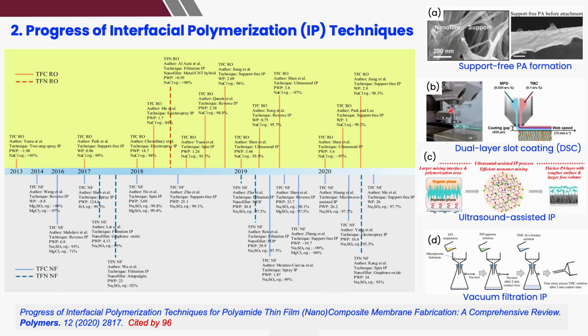And we have researchers who use dual layer slot coating. Instead of pouring the solutions one by one, they form the polyamide layer almost simultaneously using two solutions. Some use ultrasound assisted IP, and our group previously used vacuum filtration IP, a technique we used mainly to produce graphene oxide incorporated thin film nanocomposite membrane. We invented this vacuum filtration technique because we want to make sure there's no loss of the graphene oxide during the process, and the graphene oxide can be well deposited on the membrane substrate surface before polyamide layer formation. However, there's a limitation on this technique, mainly on the size of the membrane we can produce.